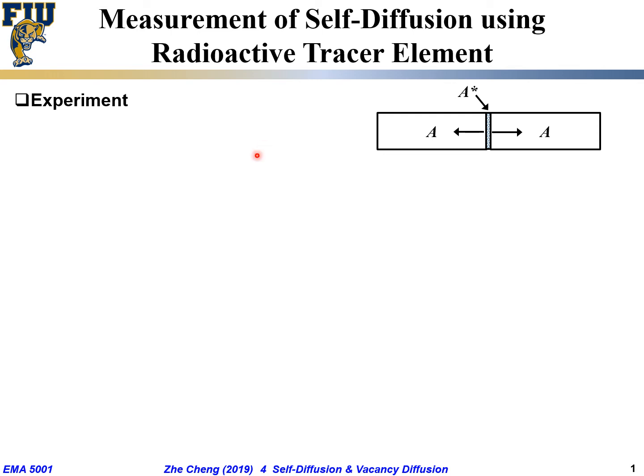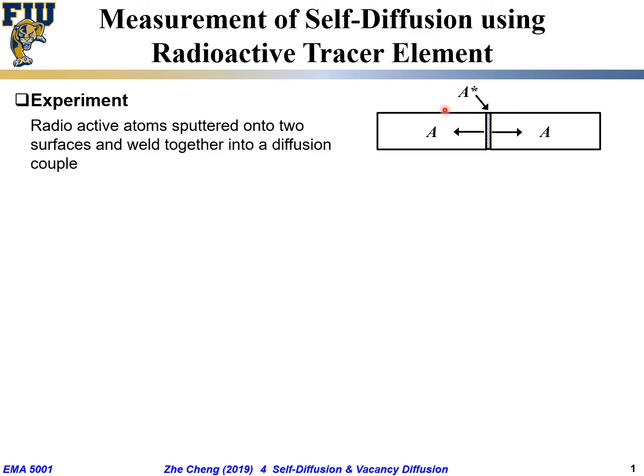So how exactly do people measure the so-called radioactive tracer diffusion coefficient, or self-diffusion coefficient? You're going to put a radioactive tracer into the material — let's say two pieces — by either ion implantation: high-energy ions implanted into the material surface, put them together, and measure over time using depth profiling, XPS depth profiling, something like that. Then you measure the concentration profile.